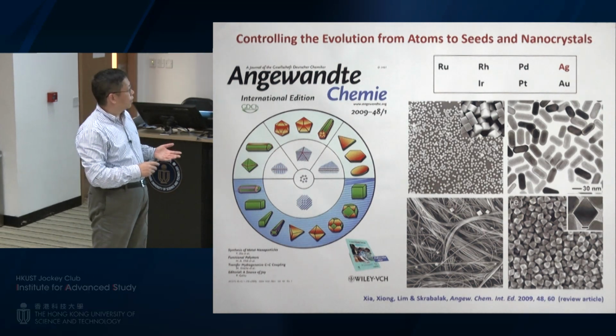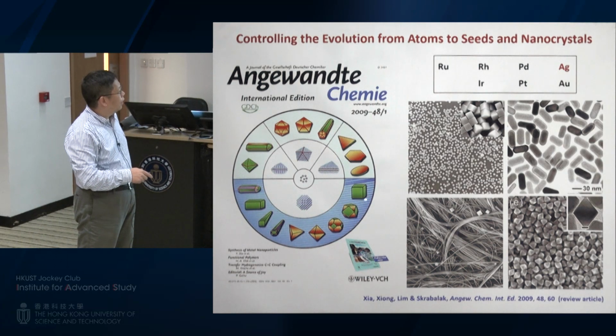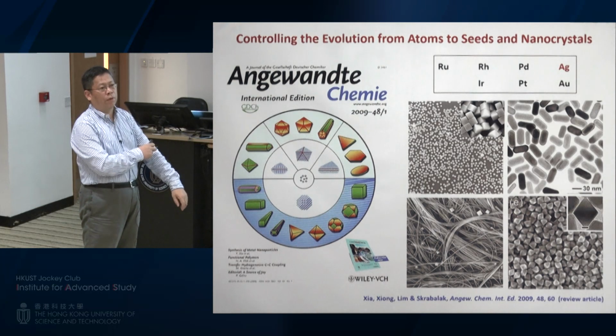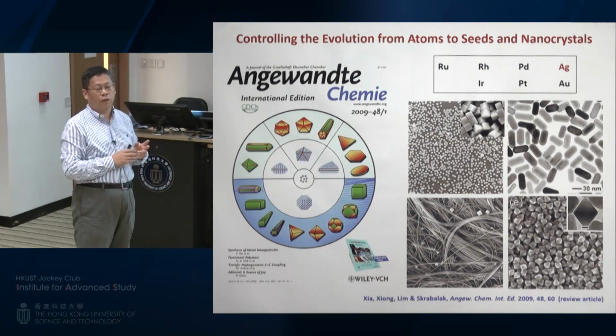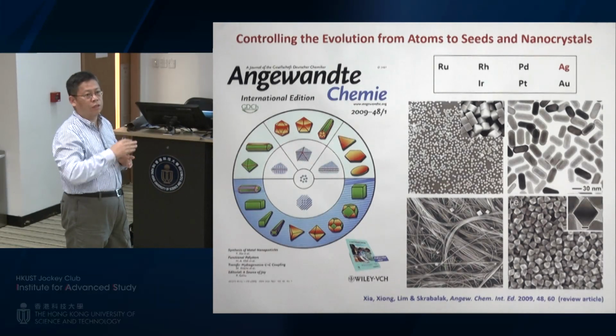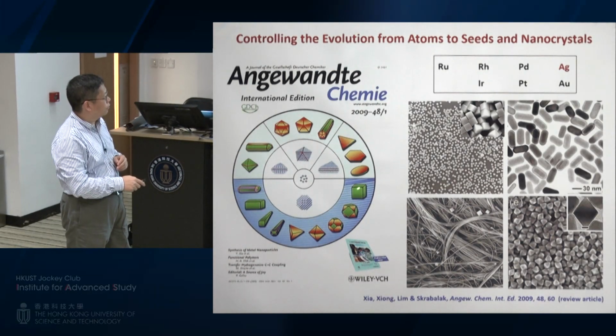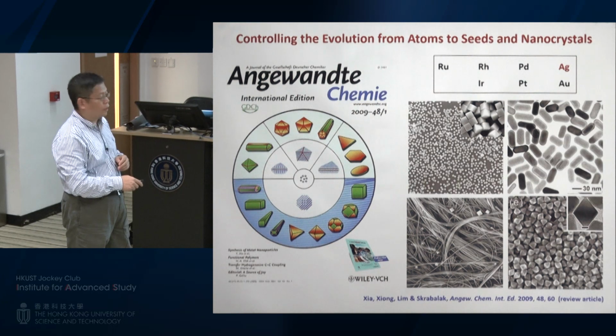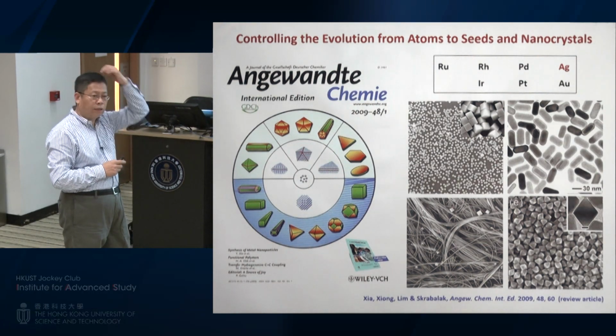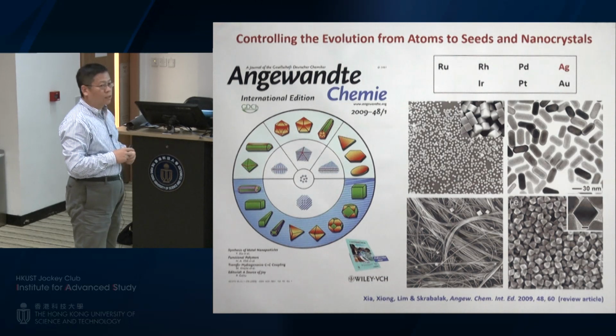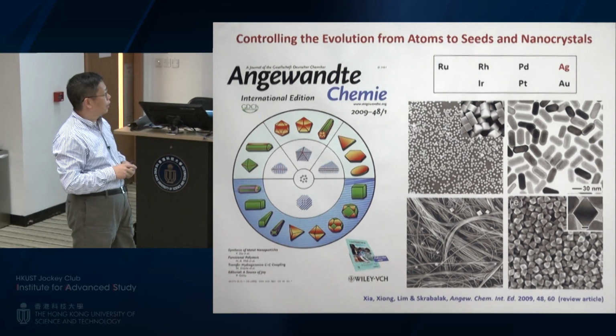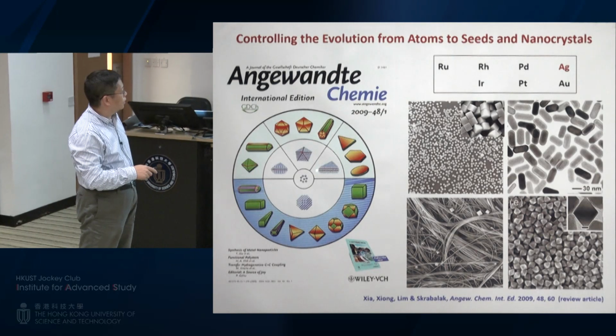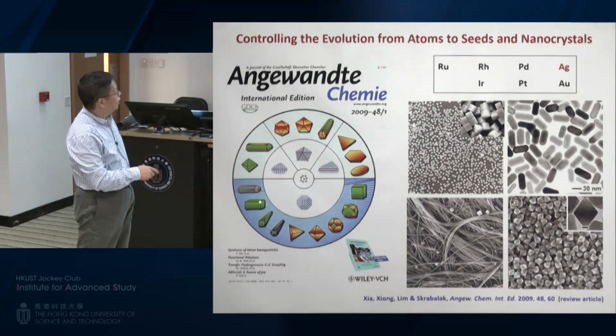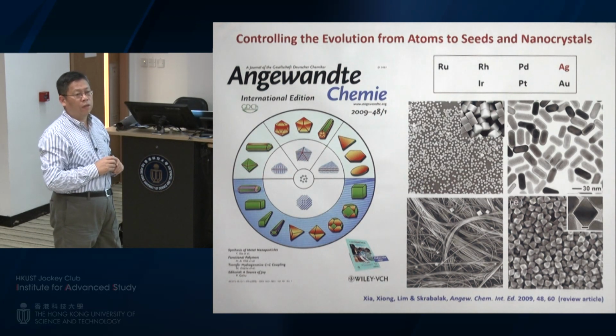So now that's also very clear. If you want to make just one shape, you have to control the nucleation. You also have to control the growth. The growth typically is going to be controlled by 2 parameters. One is the capping agent that can bind to a specific facet. Like 100 facets give us cubes, and 111 facets will give us octahedra. So the capping agent is very important. The other parameter is the kinetics. I'm going to show you some examples later. Okay, if the kinetics is not right, they may go to other shapes like this one. This particle and this particle are supposed to be similar in terms of surface structure.